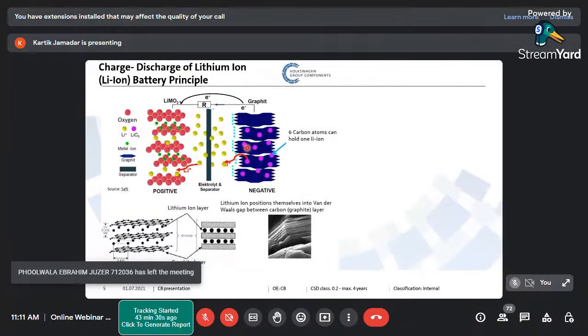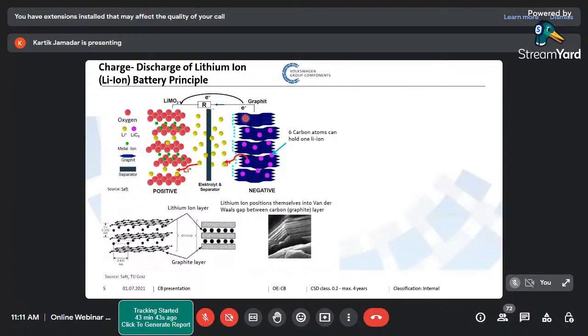There are no chances of having dendrites, and since there are no dendrite problems, the whole thing becomes very easy. The safety of the cell increased, but at the cost of weight, because as I told you, you need six carbon atoms to hold one lithium atom. It means if I need more and more lithium for more capacity, I need equivalently more and more carbon atoms. Now these carbon atoms are not actually helping me in the energy. They are just helping in the process of intercalating lithium inside the carbon. But even if they are not helping and I still need them for safety, no doubt my energy density is going to go down.